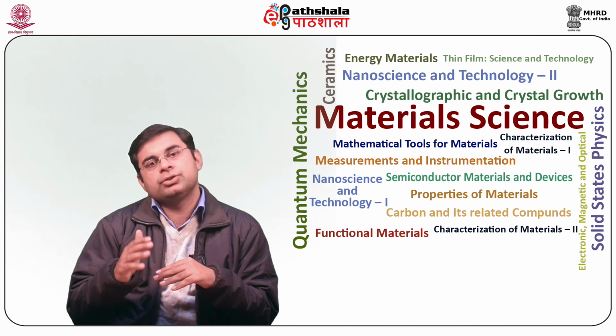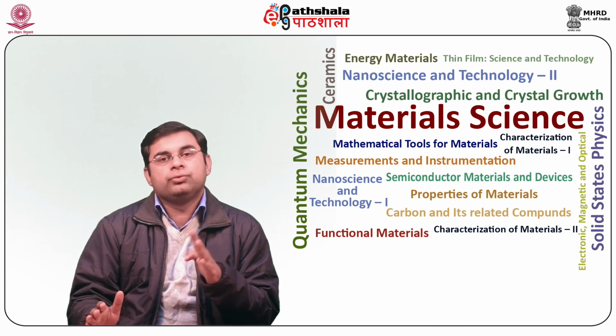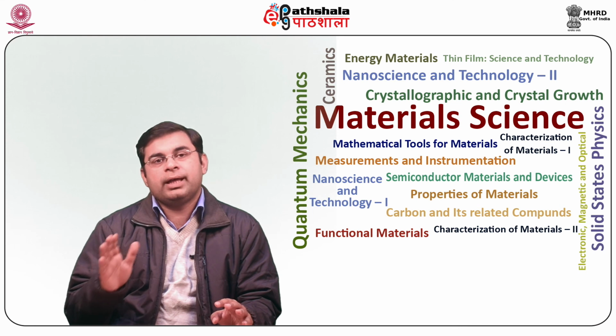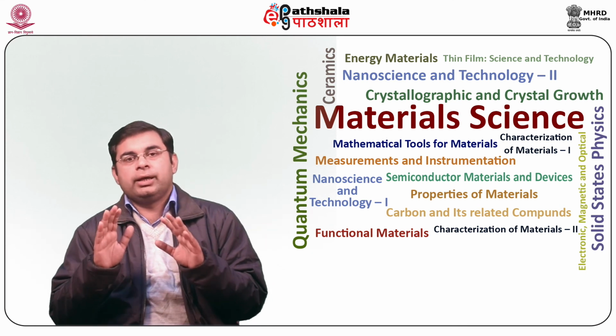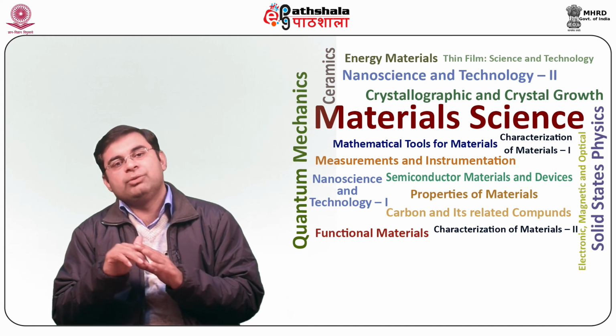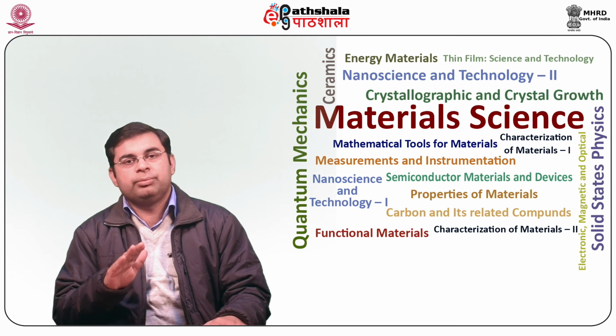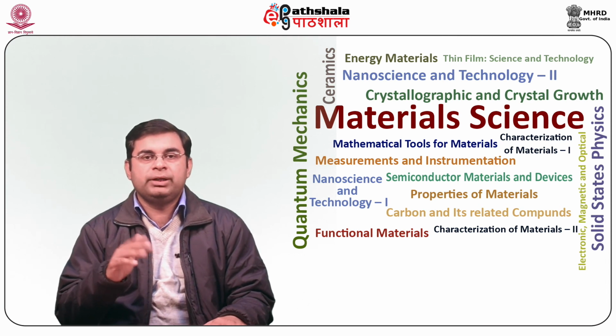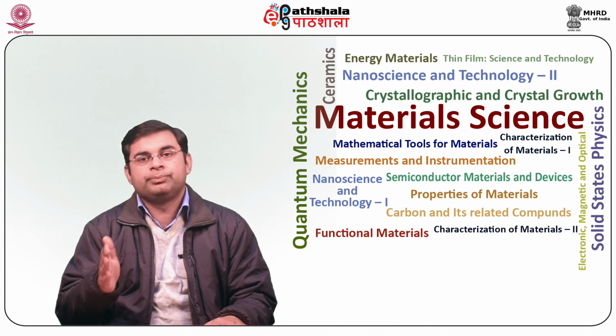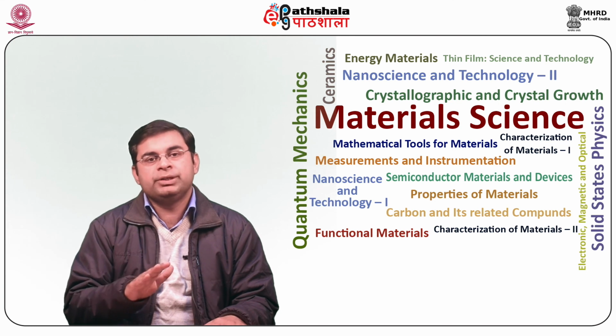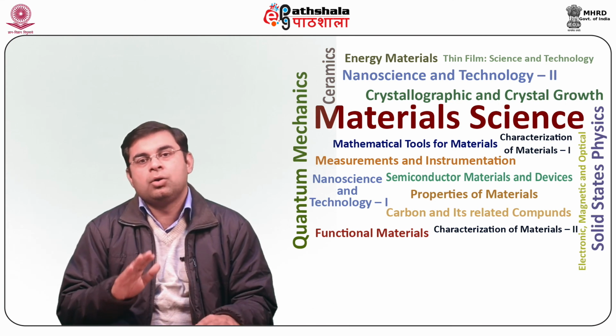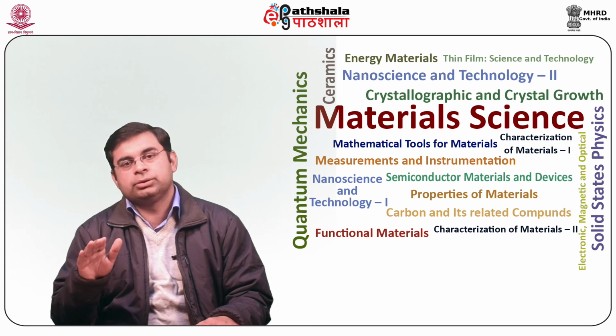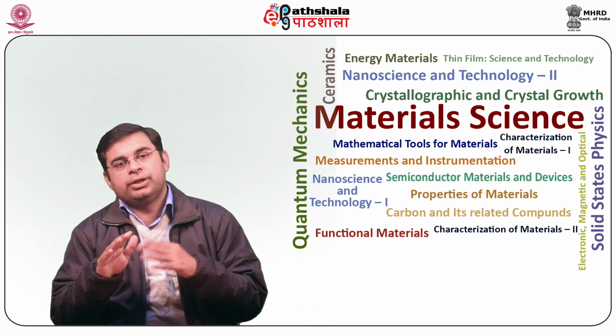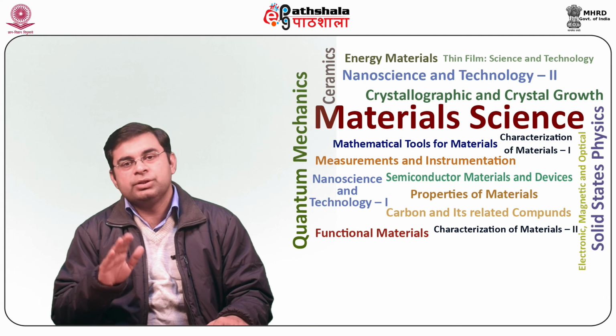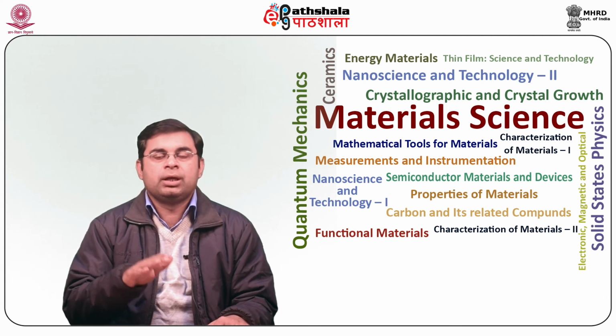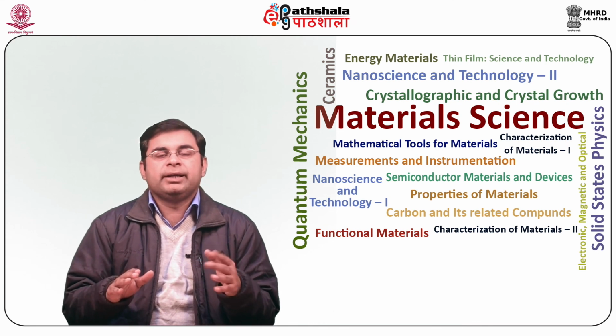Dopants can further cause a shift in energy bands with respect to the Fermi level. The energy band of a dopant having the highest concentration lies closest to the Fermi level. As the Fermi level is constant for a system in thermal equilibrium, stacking multiple layers of materials having varying properties results in novel properties caused by band bending. The most common example is the p-n junction, which has unique properties generated by band bending, which is a consequence of joining the bands in the contact region of p and n-type materials.